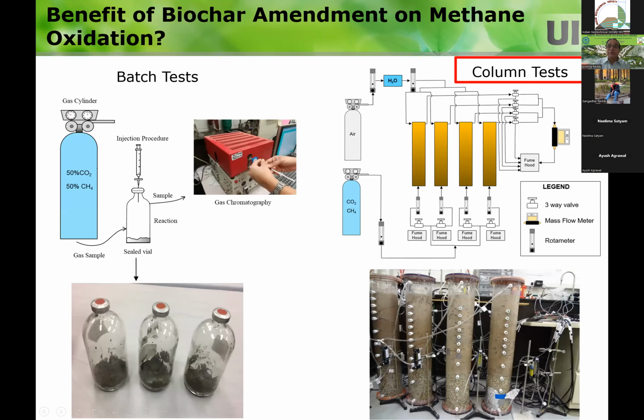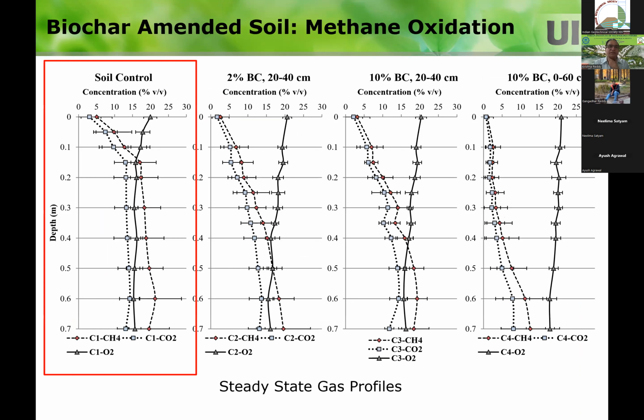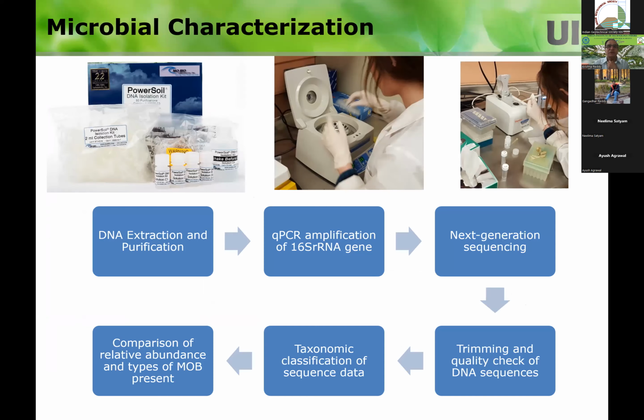So the column experiments are important, because in this one we are mixing everything. In the batch experiments, in the column experiments, gas is flowing through this column, and that's more close to the conditions. So we did the testing with the soil column, 2% biochar, 10% biochar, 10% biochar at different locations. And as you see from here, so the soil versus 10% biochar, there's a huge difference. So we concluded that the more the biochar, the better it is.